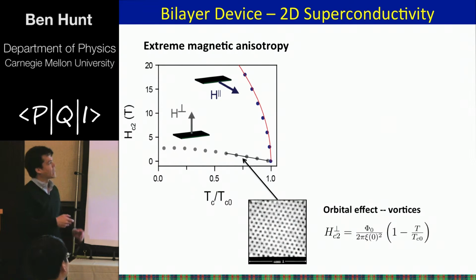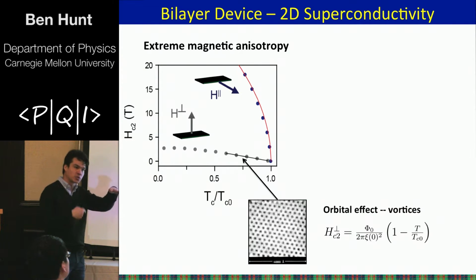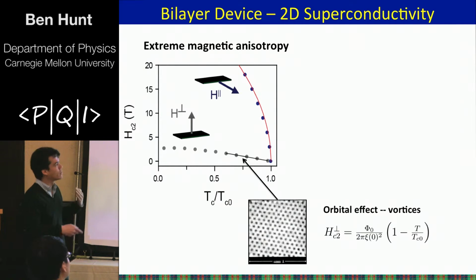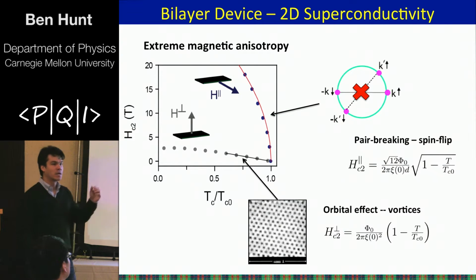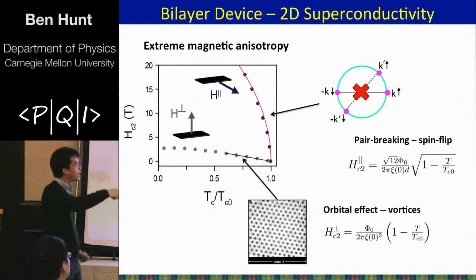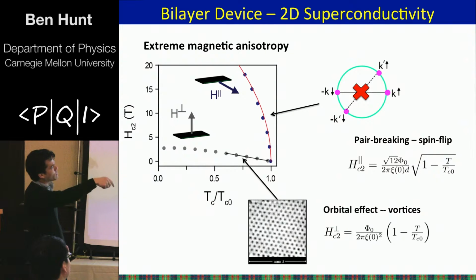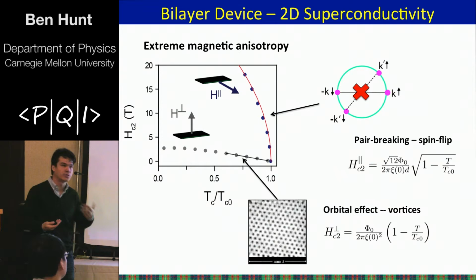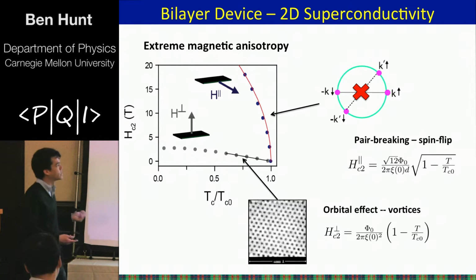Now, if you put a magnetic field in plane, because it's a true 2D superconductor, you can't actually form vortices to screen the magnetic field. And so the mechanism for destruction of superconductivity in that case is flipping the spin in the Cooper pair. And in that case, you can see that the parallel Hc2 is much, much larger. So this anisotropy really shows us that we're in the 2D limit, okay? Okay, so that was sort of our understanding of the nature of the 2D superconductivity in this niobium diselenide.